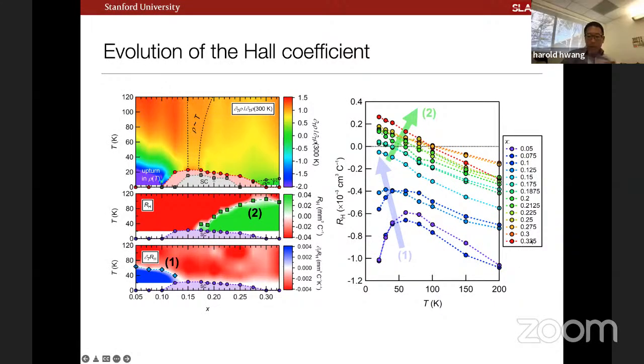Yeah, so these reddish curves here are in the overdoped regime. And so the Hall effect has a sign crossing at about 100 Kelvin, right? So this is going from negative to positive. I should say, though, even in the cuprate problem, this is observed, right? So if you look in the overdoped regime of 214 cuprates, it is actually starting out negative and crosses zero and kind of flattens out, again, on this 100 Kelvin scale. At least as a non-expert, the Hall effect, even in the overdoped cuprate regime, doesn't seem particularly straightforward as well.